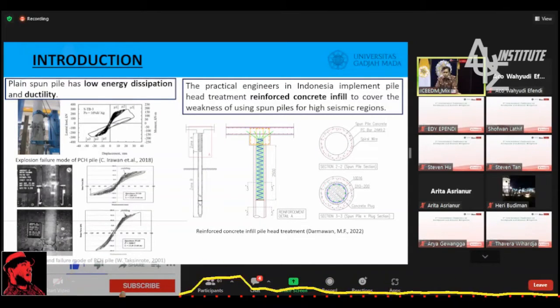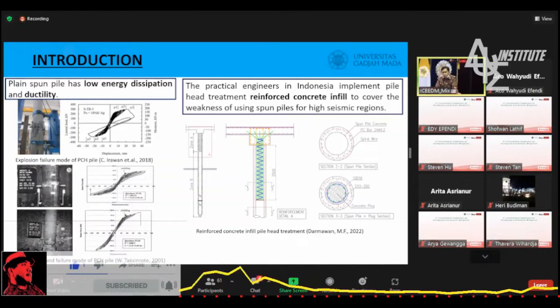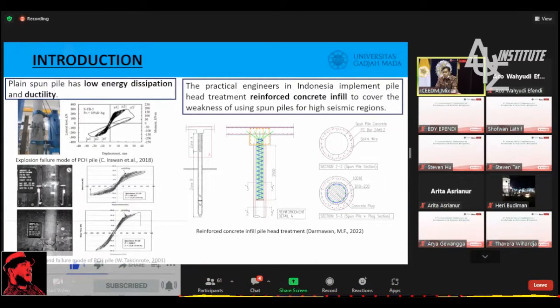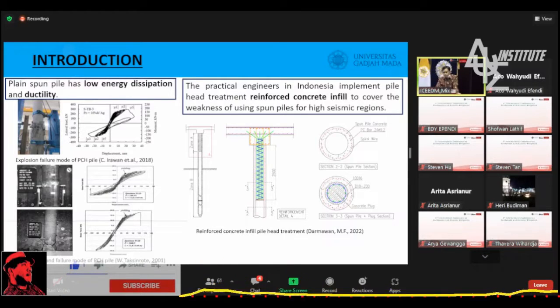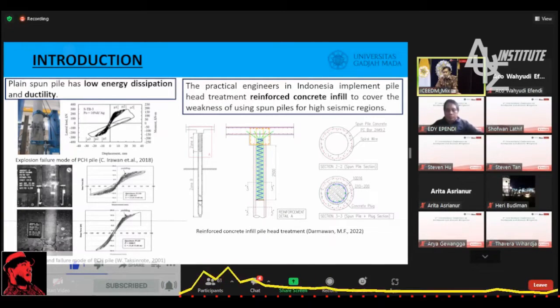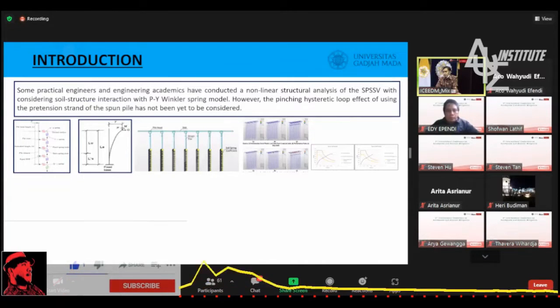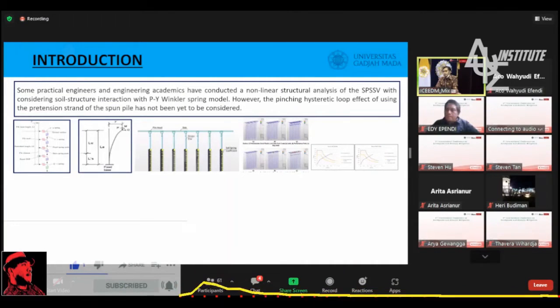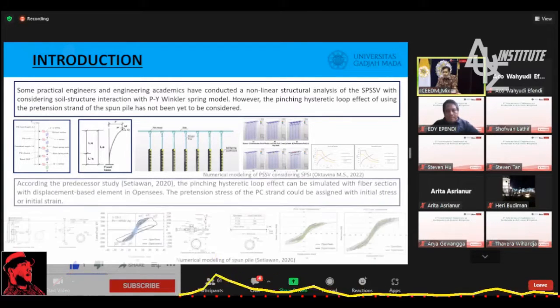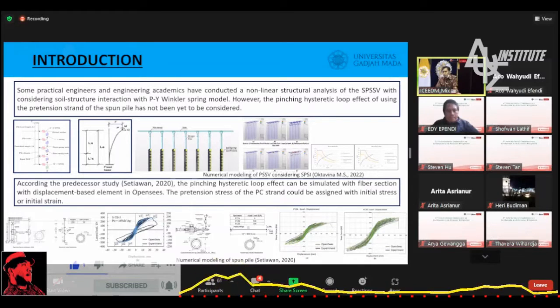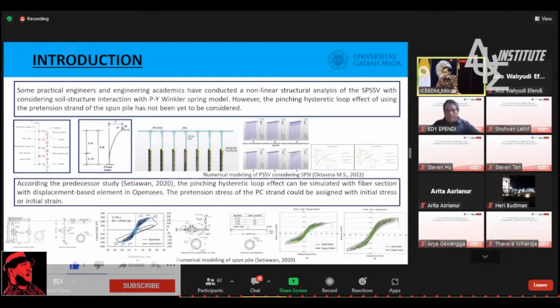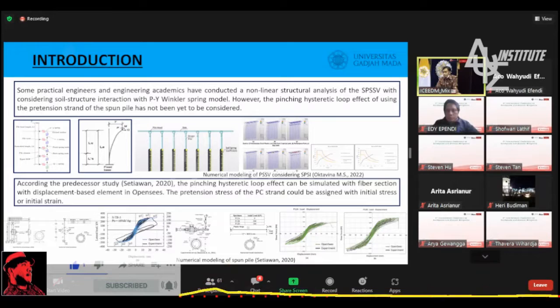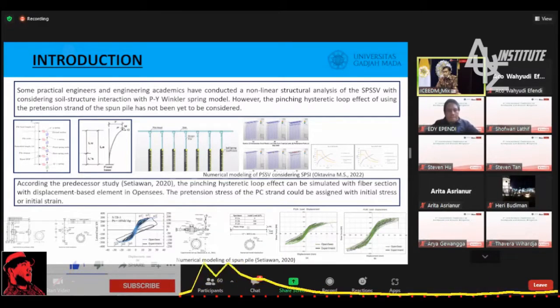Also, some previous researchers made a numerical model considering soil structure interaction to accommodate the near real behavior of the slab-on-pile structure, and some researchers did pushover analysis to achieve the performance points of slab-on-pile. However, the current study did not consider the pre-stressing effect that results in the pinching hysteresis loop or low energy dissipation. In another previous study, a numerical model of the spun pile has been conducted by considering the pre-stress effect, so it can achieve good agreement with the experimental result with pinching hysteresis loop.